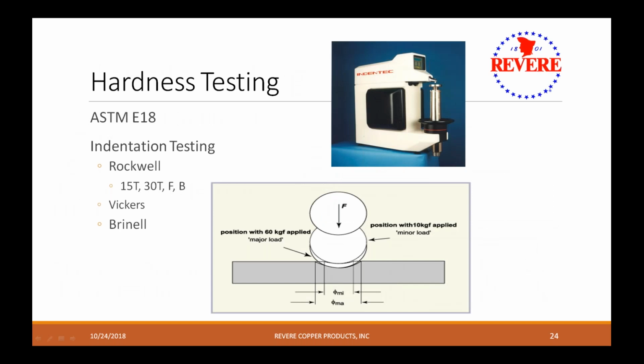Hardness testing, if a customer asks for the hardness, we do a Rockwell hardness test. There's other types of tests, different scales, but within the Rockwell, there's the 15T, 30T, F, and B. Those are dependent on the gauge of the material. So you can't apply the same amount of force to a really thin gauge as you can to a thicker gauge. So that's the difference in the scale there.